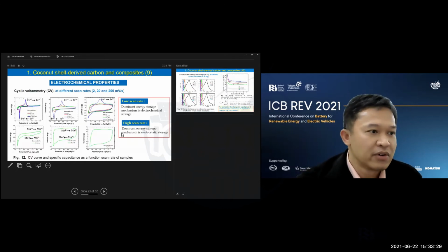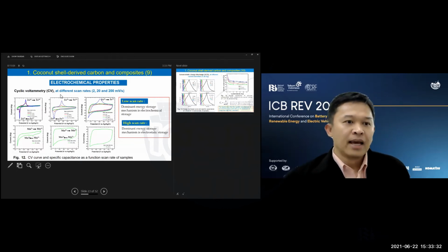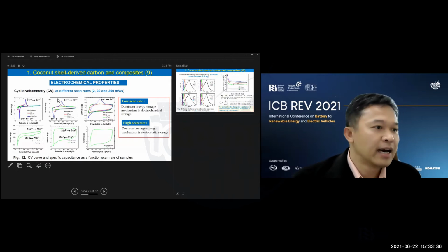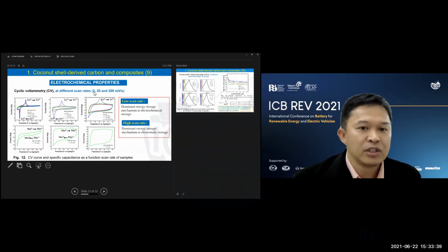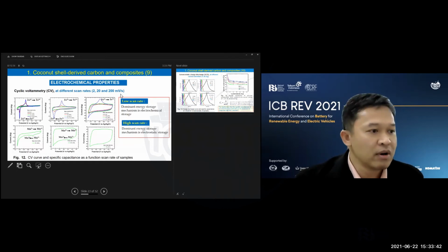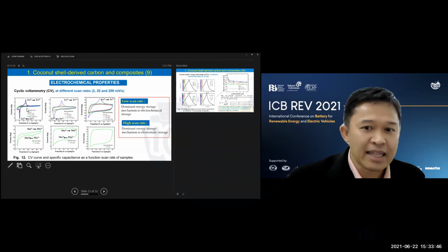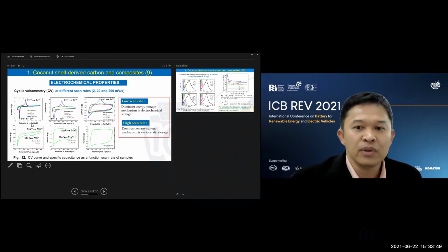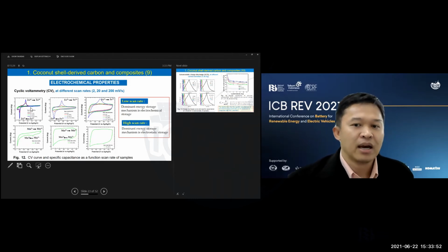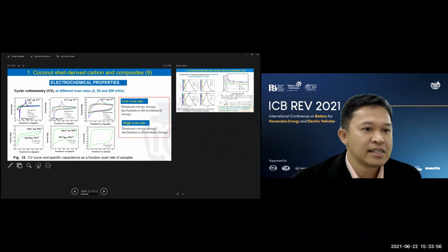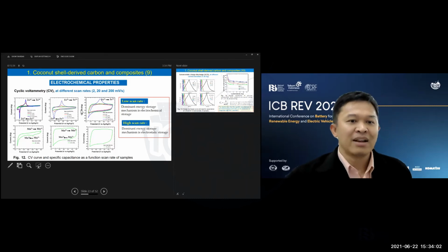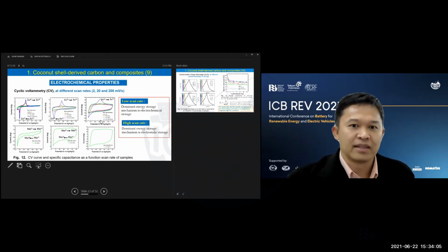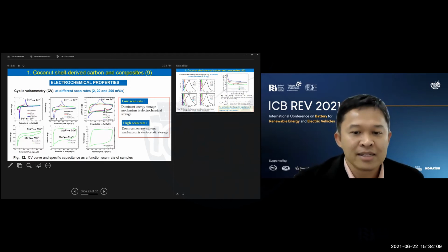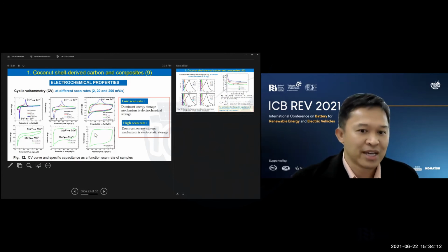And these are the results of the electrochemical properties. For the cyclic voltammetry or CV, we measure it at different scan rates, from 2 to 200 millivolt per second. At the low scan rate of 2, you can see that the dominant energy storage mechanism is the electrochemical storage. You can see the reduction and oxidation peaks. And at the higher scan rate, for example, at 200 millivolt per second, the dominant energy storage mechanism is the electrostatic storage. You can see the larger window from this figure.